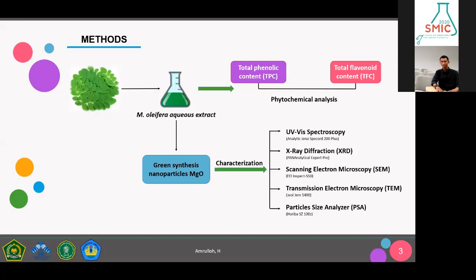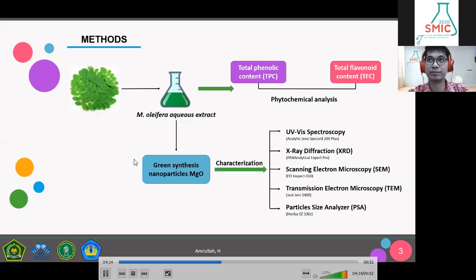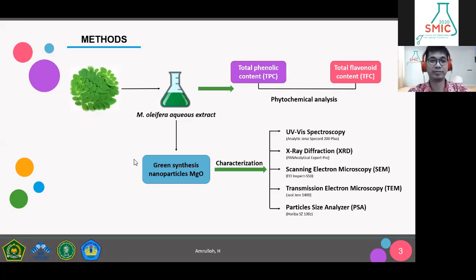The synthesis of magnesium oxide nanoparticles was initiated by adding 10 milliliters of extract into 10 milliliters of 1 millimolar magnesium chloride hydrate solution and stirring at 600 rpm at 90 Celsius. The precipitate formed was separated from the mixture by centrifugation and then washed using ethanol. The washed precipitate was then dried using an oven to remove any residual water and ethanol. After drying, the precipitate was calcined at 600 Celsius for 5 hours. The synthesized magnesium oxide nanoparticles were then characterized using UV spectroscopy, X-ray diffraction, scanning electron microscopy, transmission electron microscopy, and particle size analyzer.